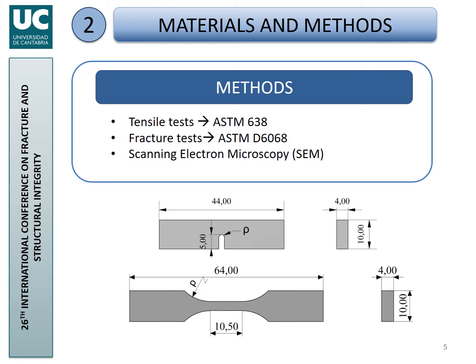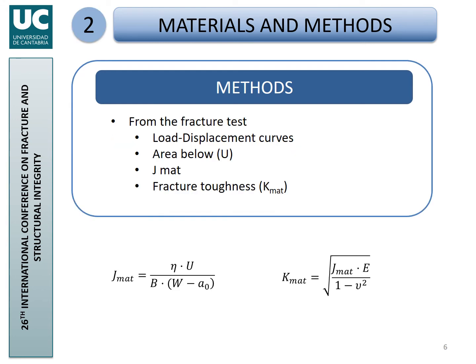We completed tensile tests as explained on the paper and fracture tests, following in both cases the corresponding testing standard, ASTM. You may see the corresponding geometries on the figure, and also we completed the research with the scanning electron microscopy analysis of the fracture surfaces in order to relate the macroscopic observations with what is happening on the fracture surface.